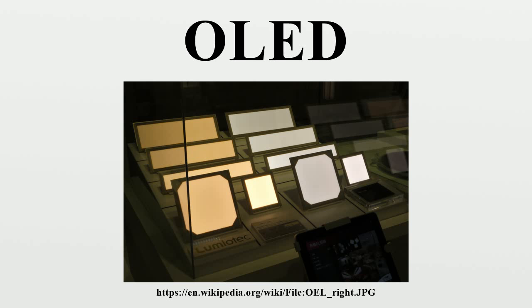Experimental research has proven that the properties of the anode, specifically the anode-hole transport layer interface topography, play a major role in the efficiency, performance, and lifetime of organic light-emitting diodes. Imperfections in the surface of the anode decrease anode-organic film interface adhesion, increase electrical resistance, and allow for more frequent formation of non-emissive dark spots in the OLED material, adversely affecting lifetime.